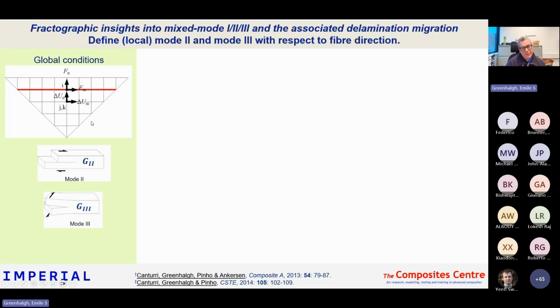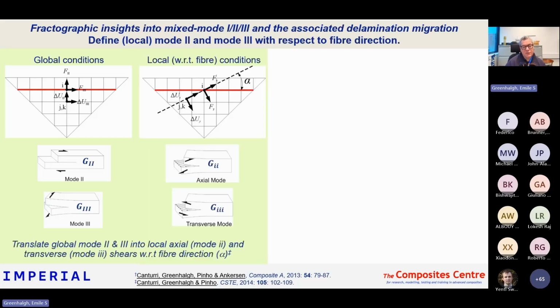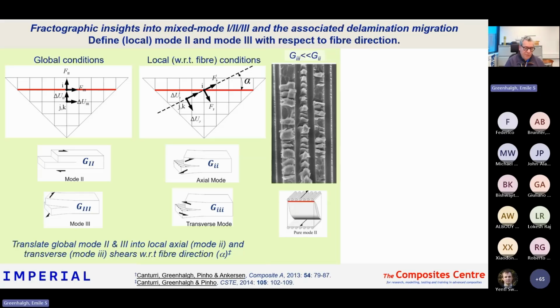But because delaminations like to grow along the fibers, we defined a different, more local mode 2 and mode 3, where the mode 2 component, we've used small letters here for this, is along the fiber direction, and the mode 3 component is transverse to that. And this shows some nice correlation with the fracture morphologies that we see.